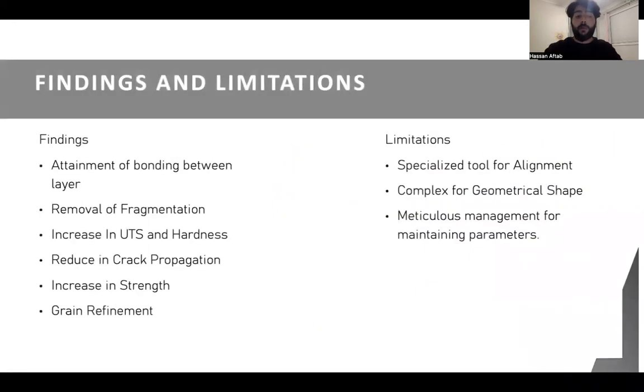So after this experiment, we have some findings and limitations. Coming to the findings, AARB successfully achieves bonding between layers of different thickness. AARB helps to reduce fragmentation in the material. The asymmetrical deformation influences plastic flow and strain distribution, minimizing the occurrence of localized fracture and fragmentation. ARB contributes to an increase in both UTS and hardness of the material. The refined grain structure and increased dislocation density lead to higher UTS and hardness values.